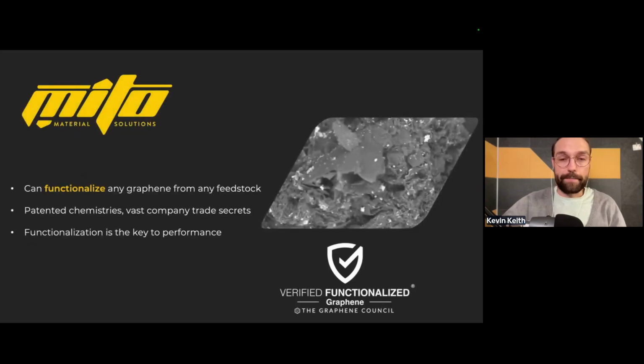At Mito Materials, what we do is we source any of these graphenes from the market, from any feedstock. We functionalize on top of them to make them more polymerically compatible. So when we have a product idea or a customer comes to us with a certain need, they say they need increased mechanical performance or thermal interaction, we look at our feedstocks available that we have quantified and qualified for our own internal processes according to our own standards and ISO standards. And we pair that with certain chemistries to better compatibilize those to then interact and disperse into those systems. We have patented chemistries as well as a vast array of company trade secrets.